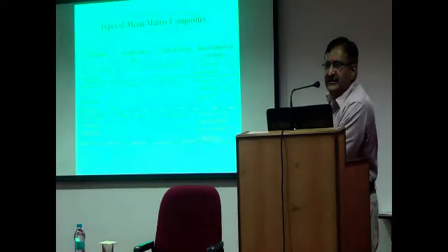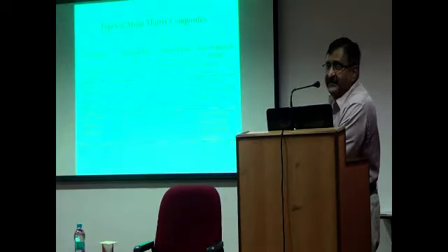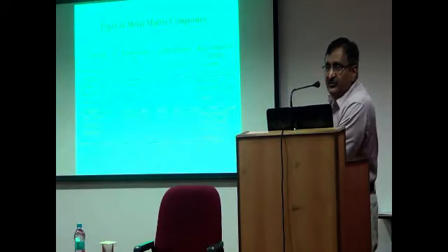One of the major difficulties with this particle reinforced material is the ductility, the toughness. Because of the 10 to 30 volume fraction of these coarse particles, it limited the ductility of the material. When you limit the ductility, the formability of the material is restricted. You cannot make it into the shapes that you want. You cannot produce a thin section. There are difficulties, so the problem of toughness. But nevertheless, these materials were used. But the challenge was to overcome all those difficulties. I'll show you a theoretical basis in my slides in the course of the lecture.